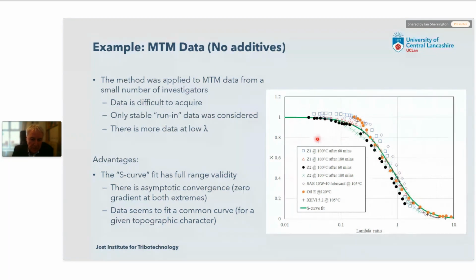The great thing about this curve is that it's got full range applicability, so it will run us straight from boundary lubrication through to full fluid film lubrication. And we have asymptotic convergence between the various regimes, which you don't always get if you use other models. And finally, one of the nice things is that this is for lubricants that don't contain additives. It also seems to collapse reasonably nicely onto one fit curve, which is convenient for modeling.